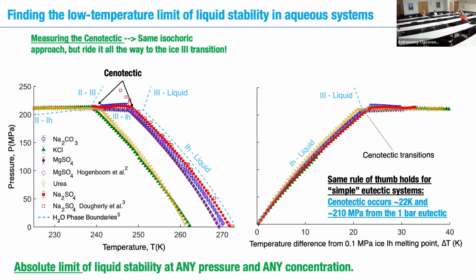And then, of course, when we collapse these curves onto a pressure depression of the eutectic temperature axis, like we did before, we see the exact same rule of thumb actually holds all the way to the cenotectic point for a variety of different systems.